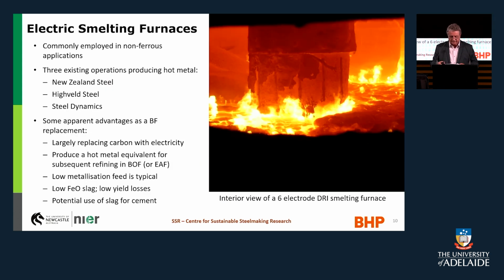Right, so now we get onto the good stuff, which is the smelting part. And so DRI feeding an ESF to make hot metal may have its place in integrated steelmaking operations, right? So the integrated steelmakers are interested. It has some advantages for lower grade material and lower metallisations. Low FeO slag process is what it is. A little bit higher than blast furnace, but certainly nothing like a steelmaking reactor. The iron yield from mine to steel product is very high, if we take that simple option to handle the gangue by smelting it to a slag. Slag potentially useful for the cement industry.